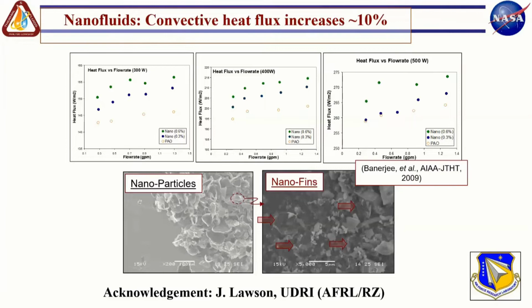So in other words, you are putting this pixie dust at less than 1% concentration, and that's enhancing your convective heat flux by 10%. But there was no surprise here, because even a decade before we did this experiment, starting with DOE labs, people had shown similar characteristics where you put nanoparticles and the convective heat transfer goes up. So we didn't really say anything new by this study.